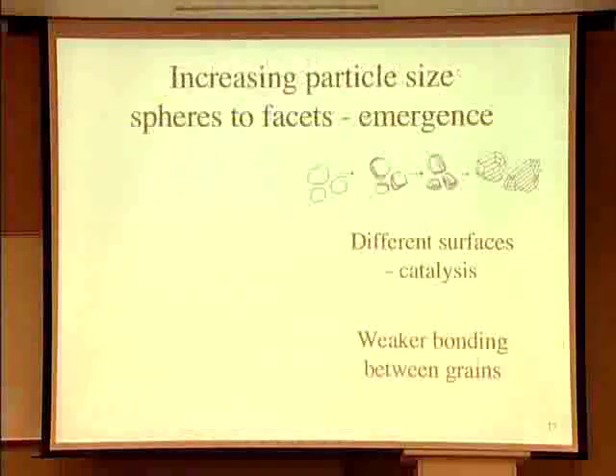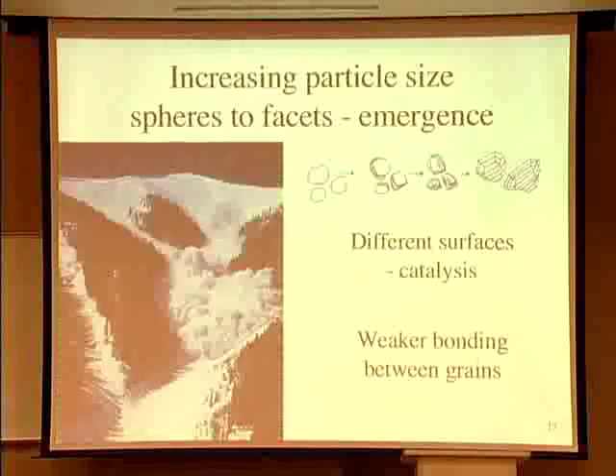If I take water and I form ice, when it's very, very small, the ice crystals are circular, spherical. The bigger it gets, the more structure it gets. In fact, I have very different surfaces as this thing gets larger and larger, going from a few nanometers to 100 nanometers. When that happens, a couple of exciting things go on: catalysis. Surfaces are very different, interactions are very different. In fact, if I look at the bonding between grains, it gets a little weaker. Well, what's an emergent property? An emergent property is what happens when I put a lot of them together. The grains between the ice crystals get weak, and I generate an avalanche.